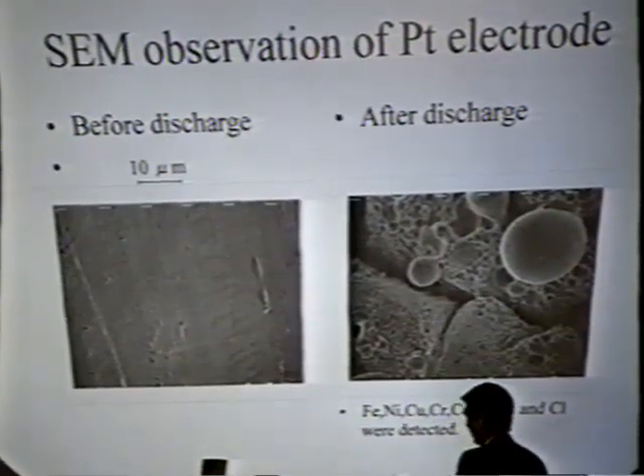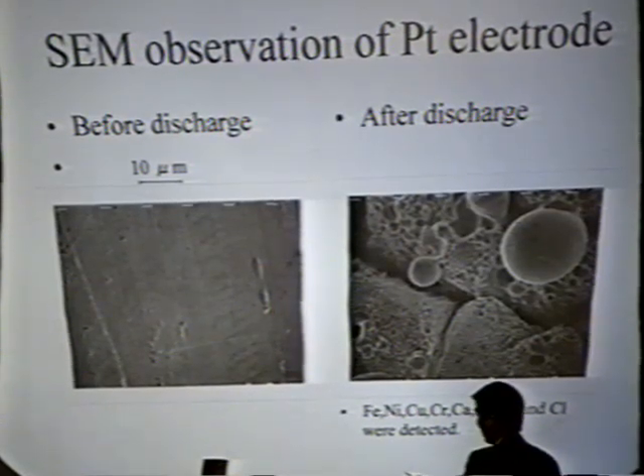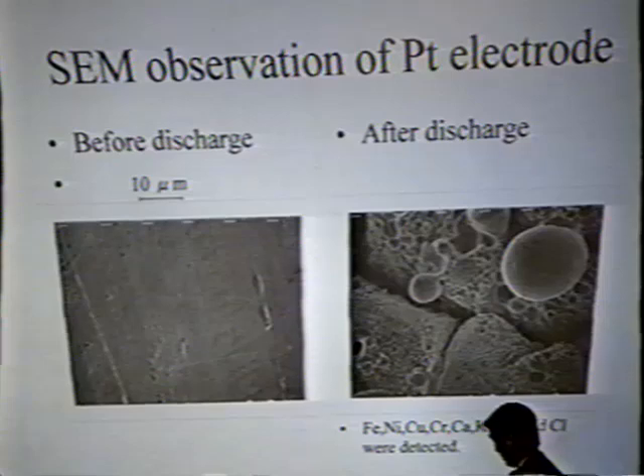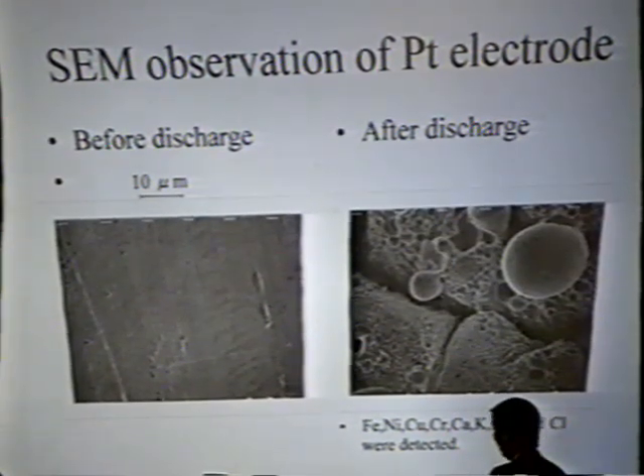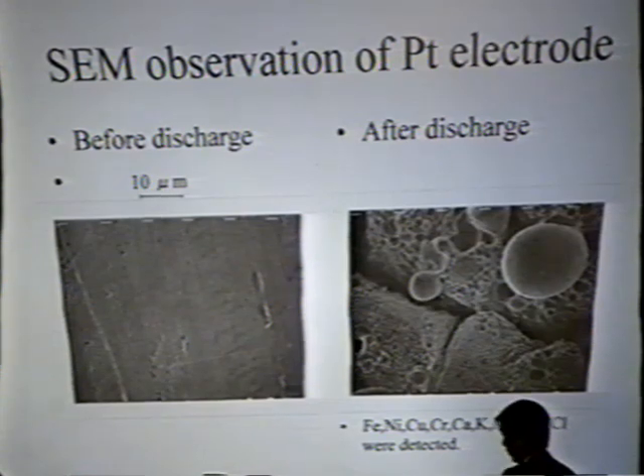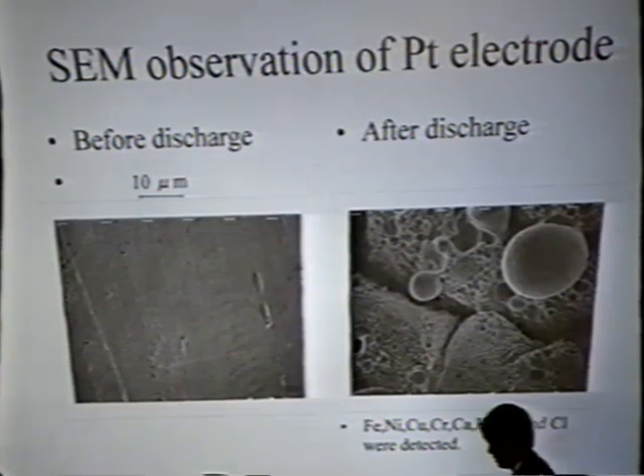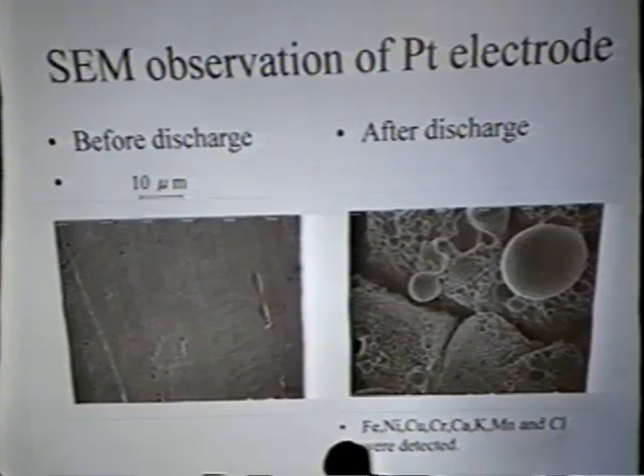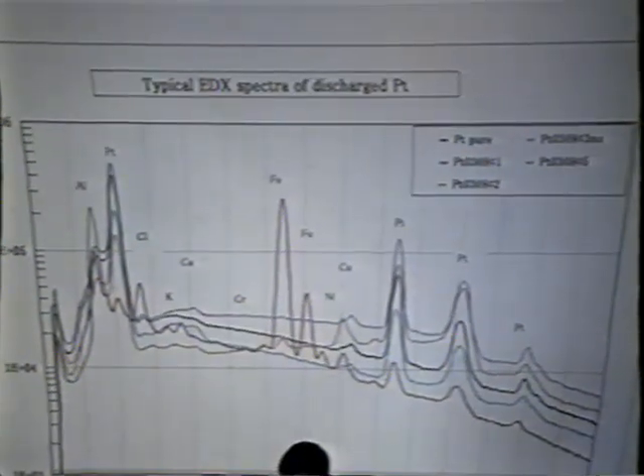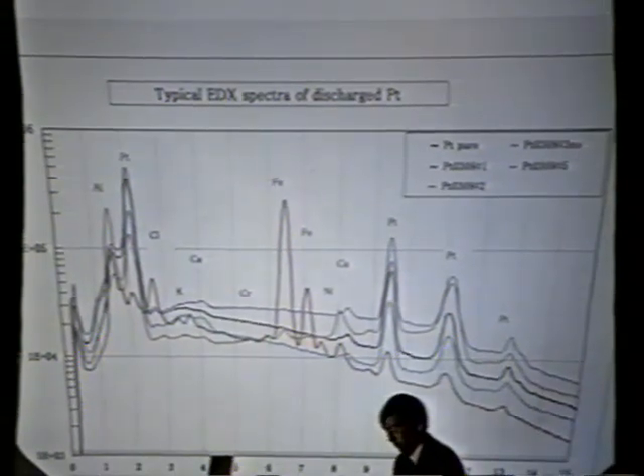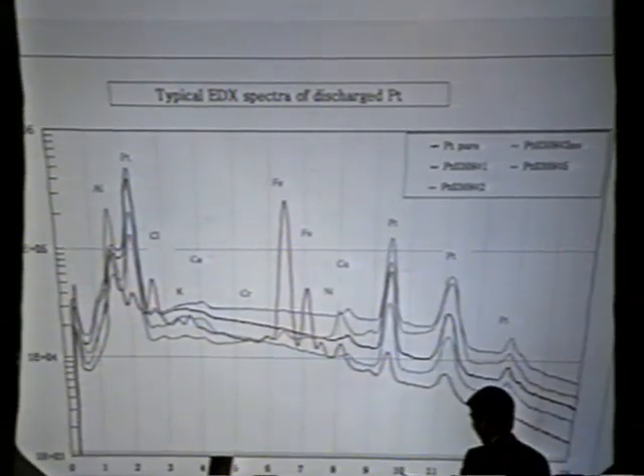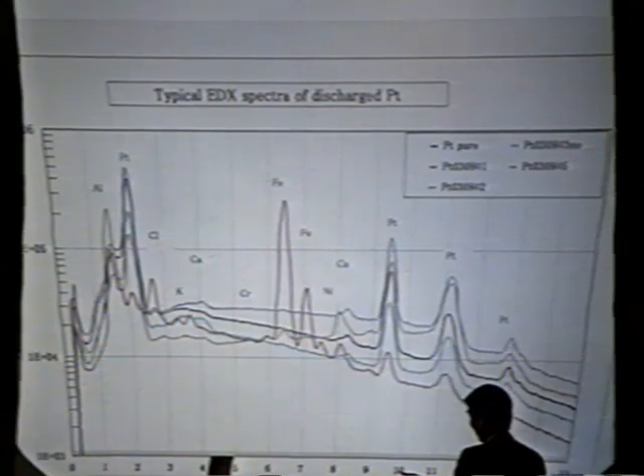These photographs show typical results of the platinum electrode surface observed by scanning electron microscope before discharge, and this is after discharge. Before discharge it is very flat and uniform, but after discharge, the surface was completely changed. The surface seems once melted. After the discharge, you can see many elements were deposited.